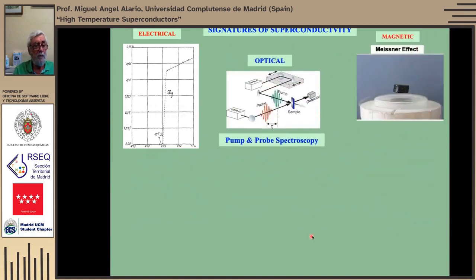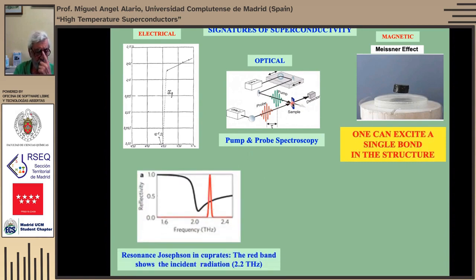That means that you can actually excite one single bond in a material. Well, signatures of superconductivity are electrical, magnetic, but we also have the possibility of studying the optical signature of superconductivity by a spectroscopy which is called pump-probe. You have the sample, and then you excite it with a pulse of the terahertz region, and then once you have excited the material, you send another beam in which you do the spectroscopy of the situation in the excited state. This is pulsed, so it's very, very brief. And then one can excite, as I say, a single bond in the structure. This excitation by the terahertz is called Josephson resonance. We'll see in a minute why it is called Josephson resonance. That will be the pulse. And then this is the resonance, the absorption. So this is the spectrum, and this came from here, and this came from here.